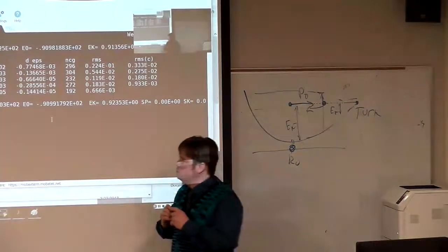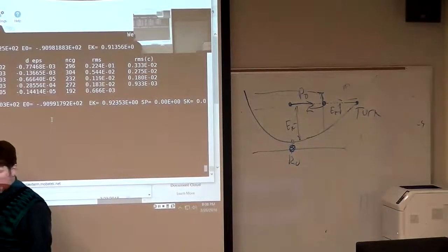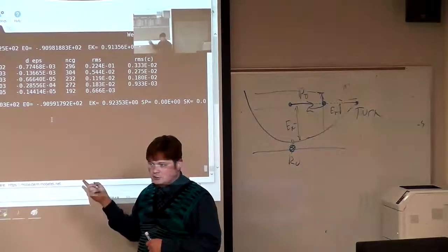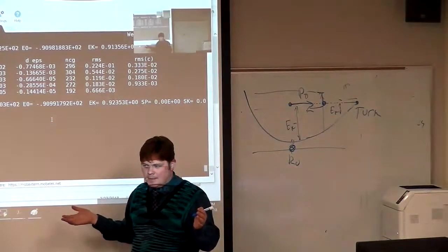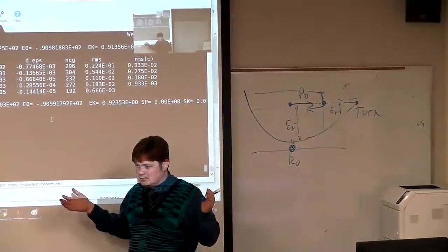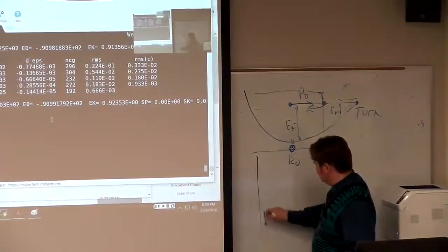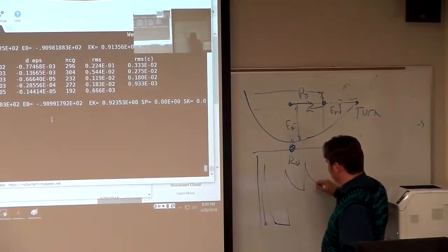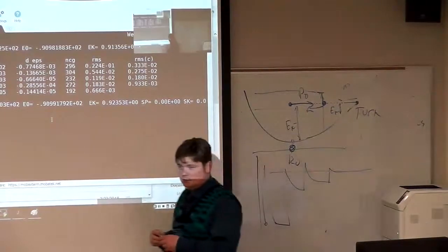So therefore, you need to run several of those kicks and blocks. What we did right now is insufficient. We did just 2 kicks. When you do it for homework or for your research, do maybe 30 steps at least, so that it has close to 10 kicks. And then if you watch temperature as a function of time, which you can do based on this data, it's set up, then drops. Then you set up and it drops. Then you set up and it drops. And then if you repeat it often enough, it equilibrates near the desired value.